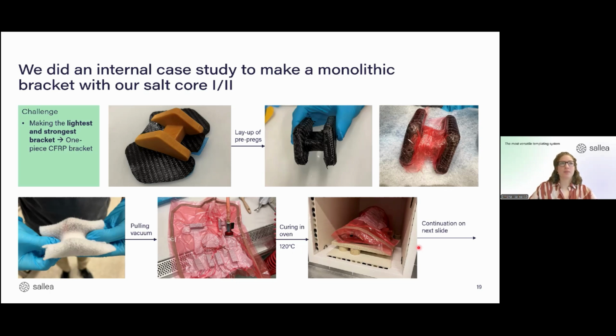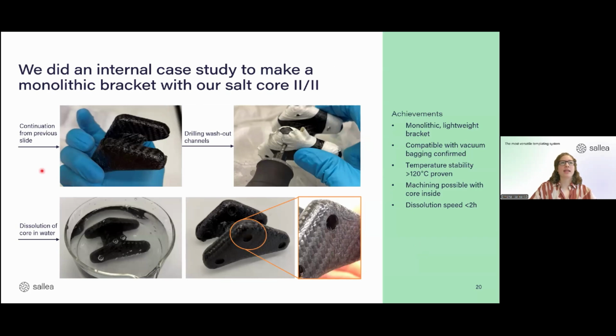And then we were removing the part from the vacuum bag. And as you can see here, this part didn't have any hole, and we created that on purpose because we also wanted to see how machinable the carbon part is after it is cured. Once for the carbon, but second also for the core that is still inside.